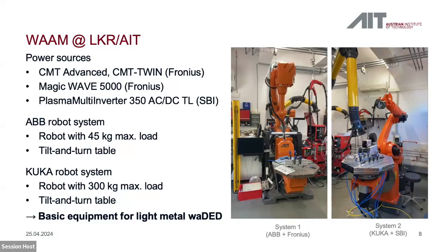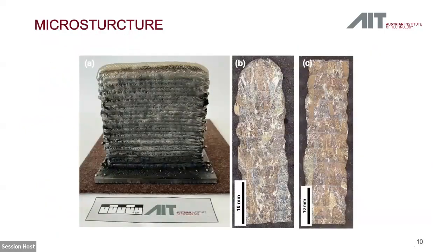All right, let's come to some results. Just a quick overview. This is a photograph of such a structure built up on a substrate. You can see some black residue on the surface. That is a result of slight aluminum burn-off. You wouldn't see that in aluminum-free alloys. On the right-hand side, you see overview images of the microstructure. As you can see, it's dominated by coarse primary grains, and you can see the layered structure. So this is the layer height of the process in the range of 5 millimeters. So we are building up really fast with comparably thick layers.